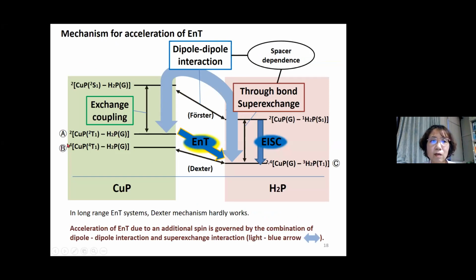Actually, this is a little bit complicated, so I would like to show a summarized figure. We have observed acceleration of the energy transfer. In this case, there are two candidates for the precursor. In the triplet quartet state, the matrix element has no acceleration component, but the triplet doublet state can mix with the upper excited state, and this final state can mix with the upper excited state, and through this process, indirectly, we can observe much enhancement of the energy transfer.